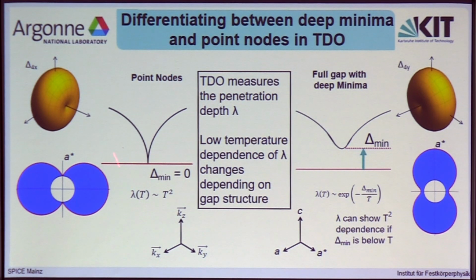Now, I will just tell you this here. For point nodes, as was the case in the Delta 4x gap structure, we would expect a penetration depth dependence of T squared, whereas for a fully gapped superconducting order parameter, we would expect to see some exponential low temperature behavior of the penetration depths. There's a small problem here: if the temperature accessible in our experiment is not low enough to reach this minimum, we could actually be fooled by seeing T-squared dependence in this case as well.